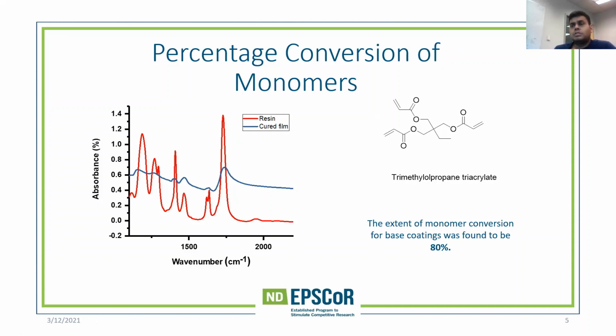Then we moved on to investigate whether we are polymerizing the double bonds. What is the extent of reaction? For that, we used FTIR, and on the left-hand side, we can see the resin curve as the red one and the cured film as the blue one. With the help of a ratio of C=O to C=C, we were able to find out that 80% of the double bonds have reacted while making the films through frontal polymerization.